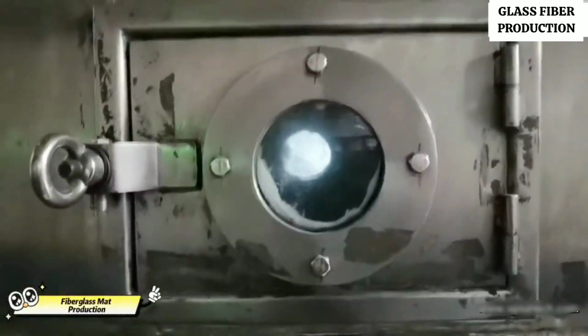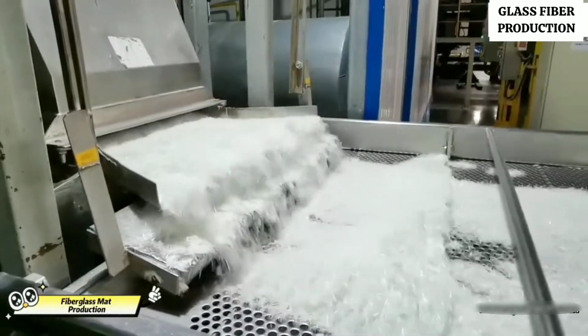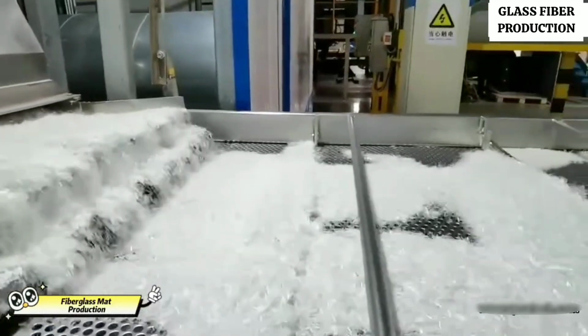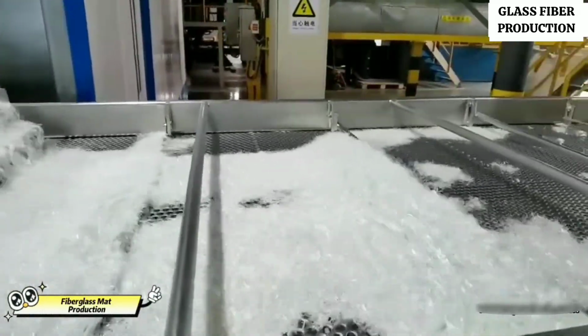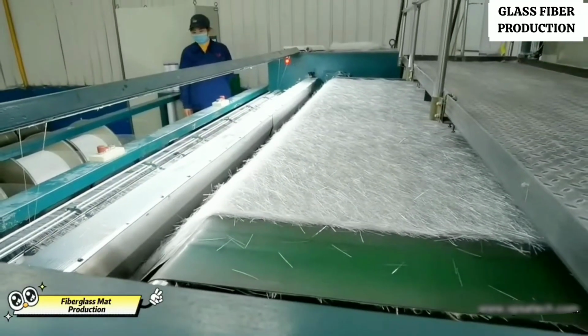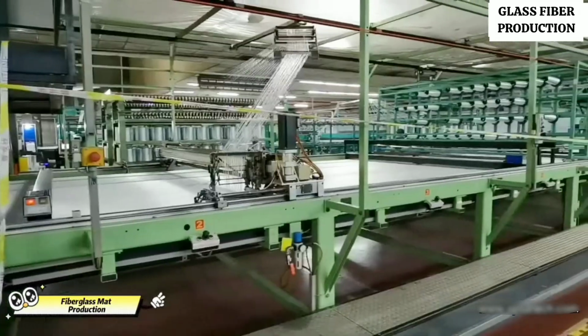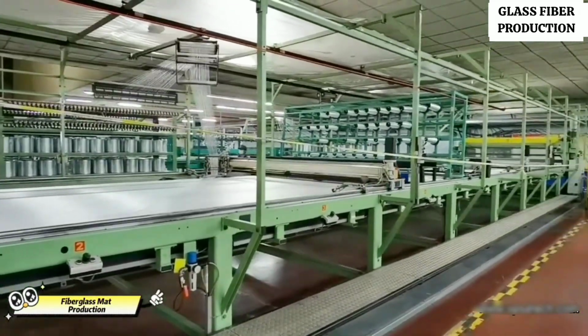Fiberglass mat production, specifically for chopped strand mats, involves cutting glass fiber rovings into 50 mm lengths, which are randomly deposited onto a mesh belt. A binder is applied, followed by drying, curing at high temperatures, and final rolling.